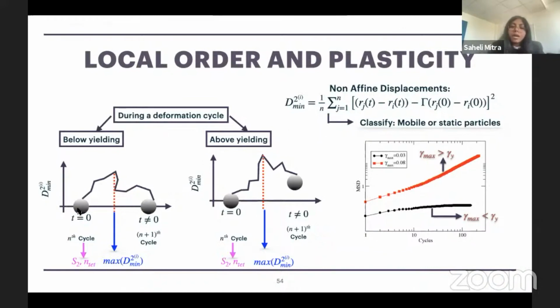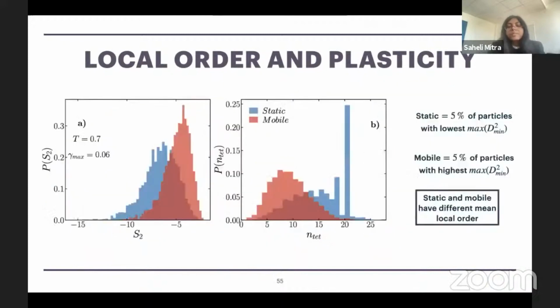Then we compare the structure it had at the beginning of the cycle. So we compare the value of S2 and Ntet at the beginning of the cycle. For that structural information, we relate it to the particles that went through maximum or minimal rearrangement, and we classify them as mobile or static particles. When we plot the distribution of initial S2 and Ntet for the mobile and static particles, we see that there is a clear difference. The mean of the distribution is different for static and mobile particles. In fact, if we look at the plot of S2, we see that for mobile particles the mean value of S2 is higher. That means on average, the mobile particles had lower structural order at the beginning of the cycle.